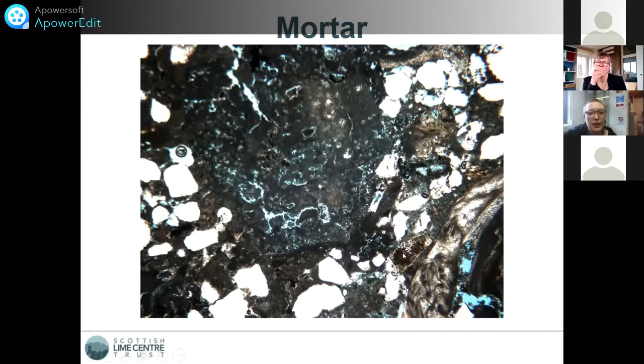And this here in the centre is a lime inclusion where you can see some crackings occurred. All these white patches are quartz, that's some of your aggregate, and another shell fragment. But the actual lime inclusion in here only contains a few bits of clinker, which just means that there was some impurity in that limestone.